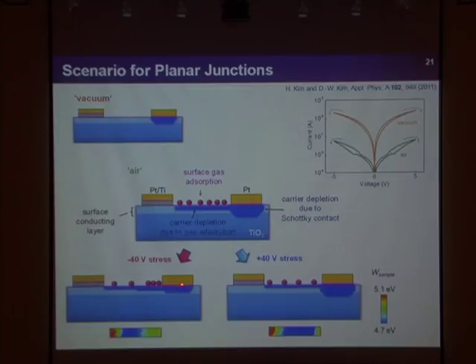Just under the electrodes, I actually have no idea, because I cannot get the work function information under this area. But in the minus 40 volt case, somehow the amount of gas adsorption doesn't change quite a lot. So this is the picture that I can propose, and according to this picture, I can explain all the resistance change behaviors.